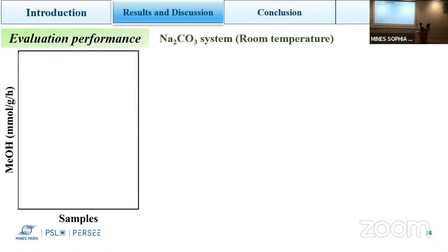So for the CO2 sodium carbonate system at room temperature, here we chose our pure TiO2, which has the same performance as P25. Our pure TiO2 is only anatase phase, and P25 is a mixed phase of anatase and rutile. Even though ours is only anatase phase, it already has the same performance as P25. It shows maybe the higher SBET is working here.